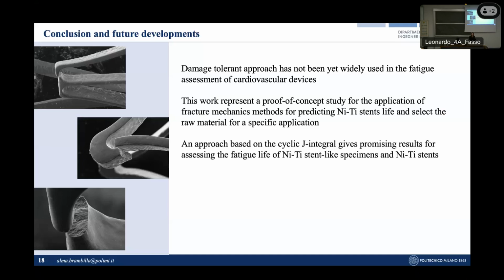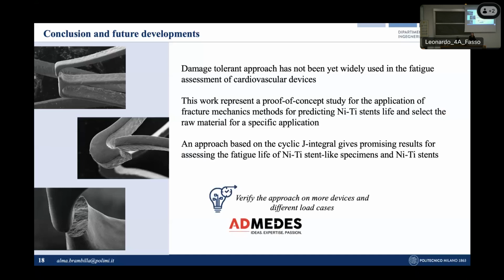So, in particular, an approach based on energetic considerations through the introduction of the cyclic J integral seems to be able to give promising fatigue life predictions of both multi-wire samples and nickel-titanium stents. And this approach can then be further verified in the future on more designs and several loading conditions, exploiting our collaboration with the manufacturing company ADMEDES.